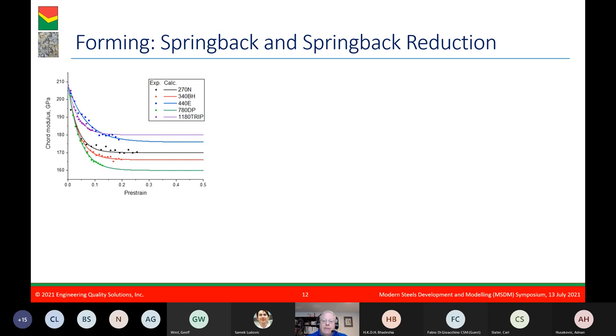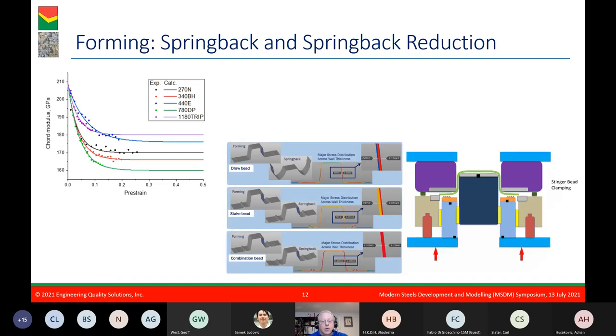As you would expect, we have an extensive section on springback and springback reduction strategies. We describe how accurate modeling of the Bauschinger effect and the decrease in elastic modulus are key inputs in achieving accurate simulations. Springback is easier to attack when you understand that the magnitude of springback is a function of the uniformity of stress distribution through the thickness direction of the wall of a formed sheet. An optimized combination of draw beads and stake beads promotes a uniform stress distribution through the thickness, which leads to improved springback control.